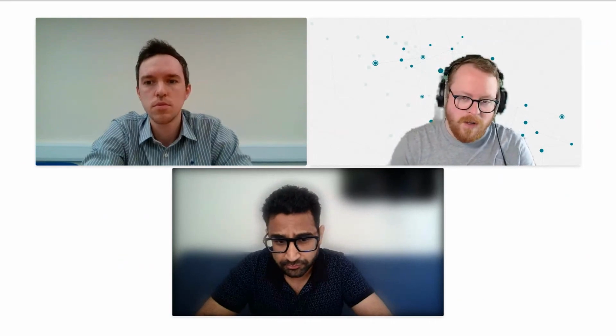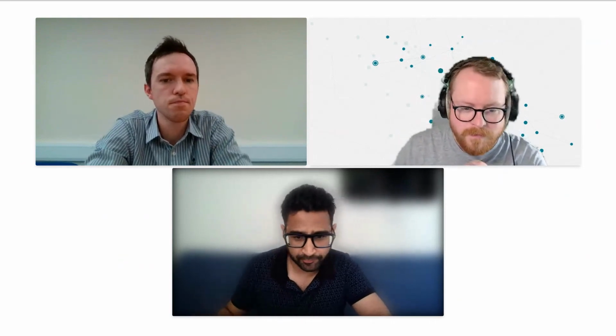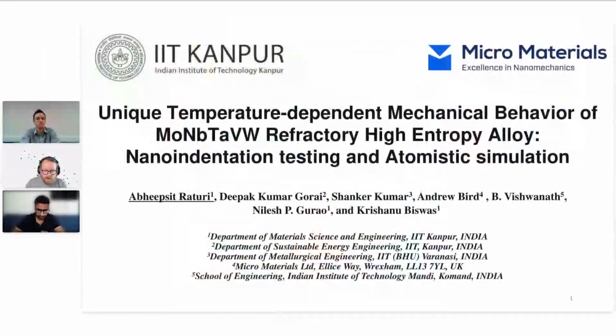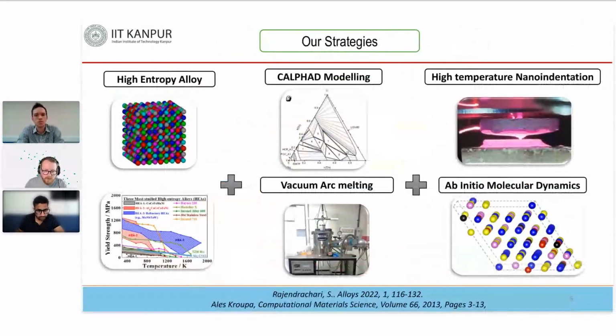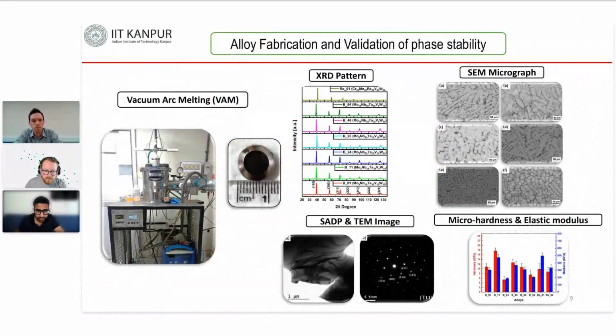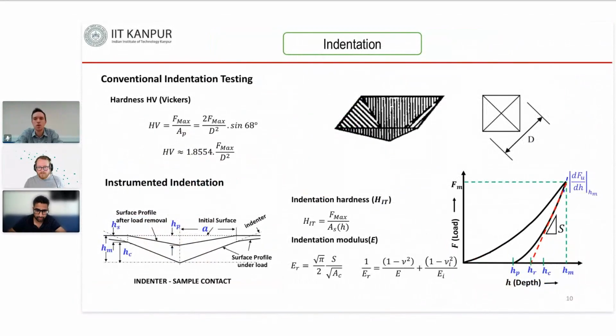We got one from Pulami, who asks, how is the Young's modulus calculated in nanoindentation? So, finding out the modulus value, we use the unloading part of the load-indentation curve. We take the slope of the unloading part of the indentation curve at the maximum load. This slope can be related to the reduced modulus, and from the reduced modulus we can find out the Young's modulus with this formula.